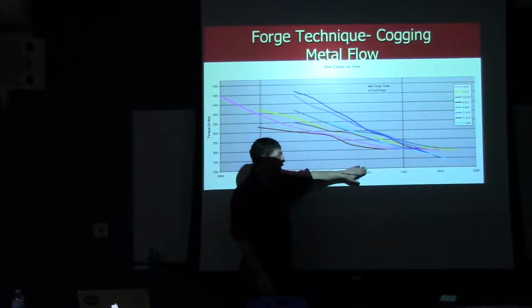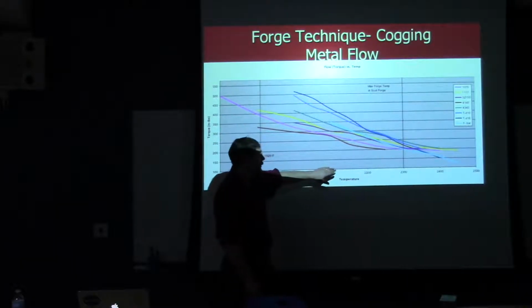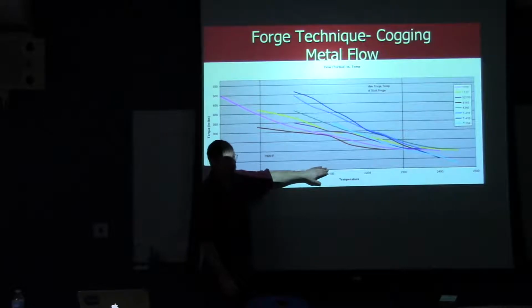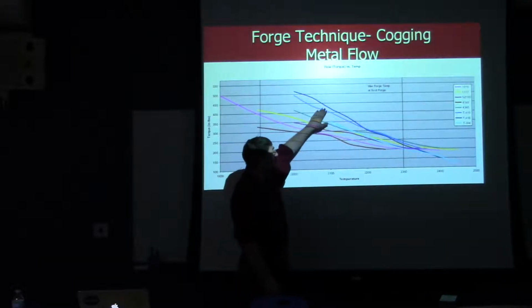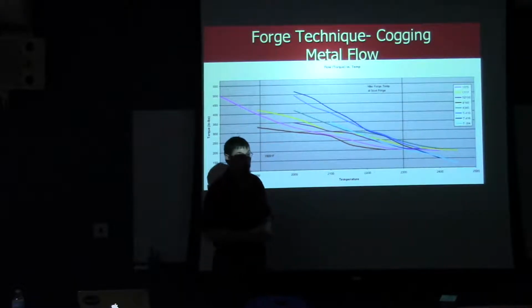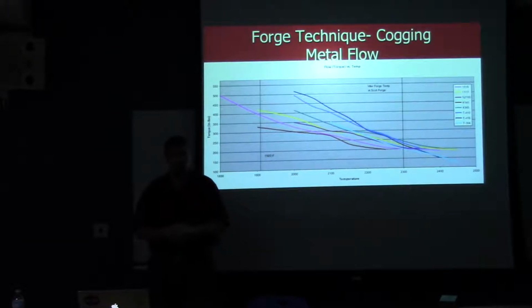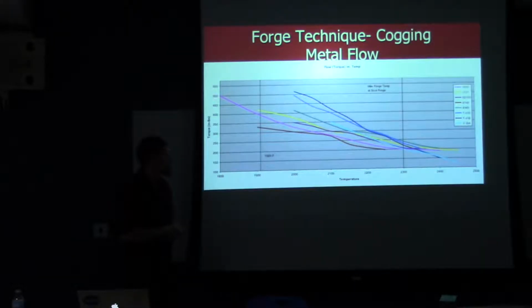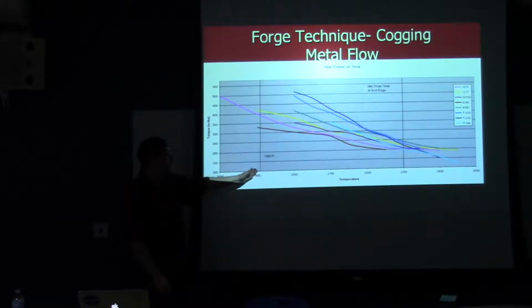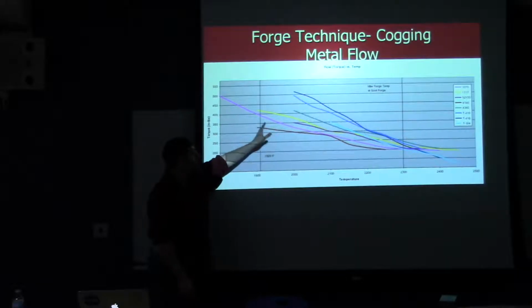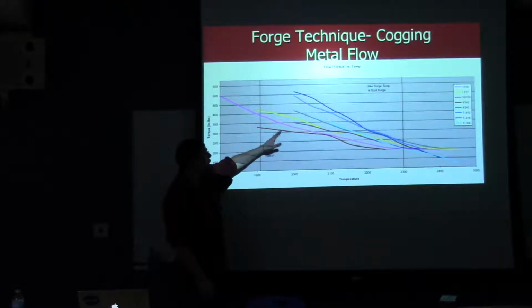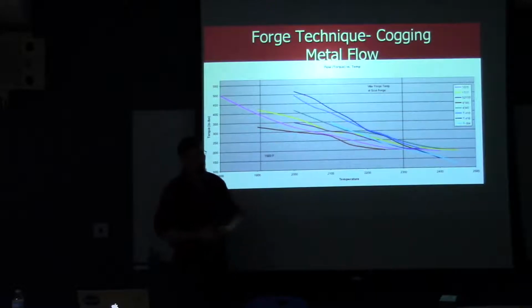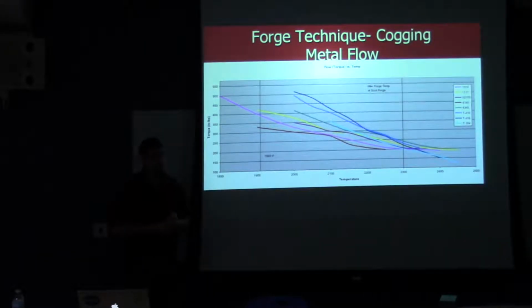So you may be down here at 2200 degrees, or for certain things you might even be down here at 2100 degrees. And now we can see that there's quite a difference in the torque or flow stress required to move those different alloys. If you're down here, which is kind of where that experiment was done, you can see that some of the grades aren't even forged at such low temperatures, but if they were, they would be really difficult to move. Are there any questions on that? We're going to go to another parameter.